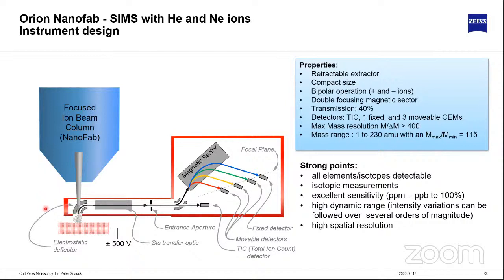And what we're typically using here as a detector, as we're using relatively low currents, we need to make sure that we have a detector setup that is constantly measuring and that we have a good transfer system or an ion extraction system that transfers all the ions that we generate into the detector. So typically what many people are using nowadays for FIB systems, we are also doing that on some instruments, is to use a TOF SIMS.